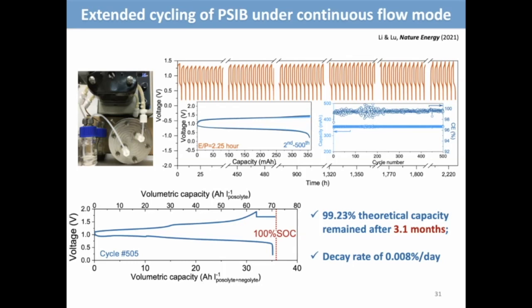And then we start using a fully flow, two-sided fully flow polysulfide iodide battery. And then we can see over the course of flow cycling, we still see a very stable performance over, again, 3.1 months. And at the end, we use a 100% SOC to check the actual remaining capacity. And we get more than 99.2% remaining capacity after 3 months.